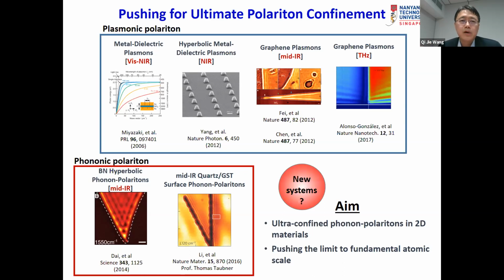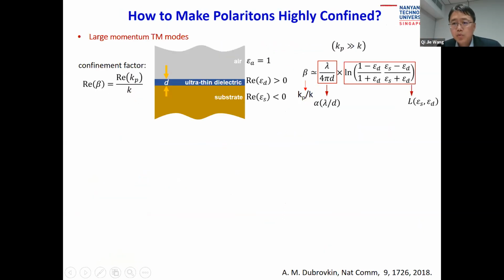and also push the limit to the fundamental atomic scale, both at the device level and in the field confinement level. So we look at this three-layer system, where the substrate consists of a negative permittivity material and a thin layer of dielectric on top, which has a positive permittivity, and air. Just looking at the Maxwell equations of this system, we can derive the confinement factor, which is defined by the wave vector of the phonon-polariton over the wave vector of light in free space. And we can simplify the confinement factor into this formula, which consists of two terms.